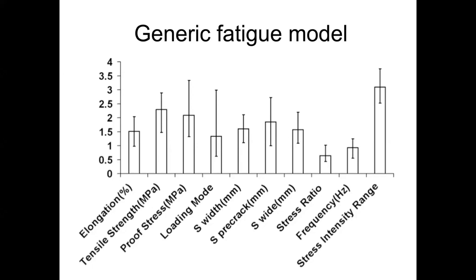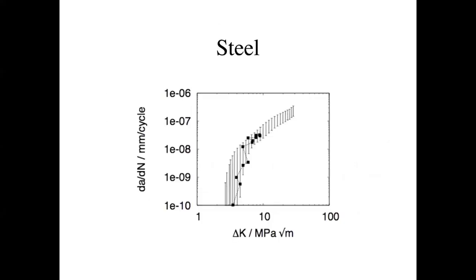So the data are all on steels, a vast range of compositions, test parameters, etc. And I'm only showing you a few slides. So the error bars here represent our calculations, and the points are unseen data. Okay, so this is the normal way of plotting crack growth rate, where you have a stress intensity range here and a crack growth rate, and it's logarithmic because that's the relationship between the crack growth rate and the stress intensity range. So you can see it predicts really quite well over many orders of magnitude of crack growth rate. And this steel, for which you see the data, was not included in the database.